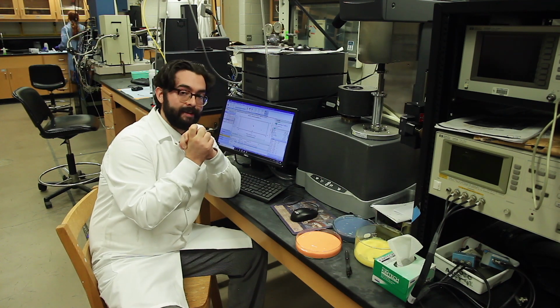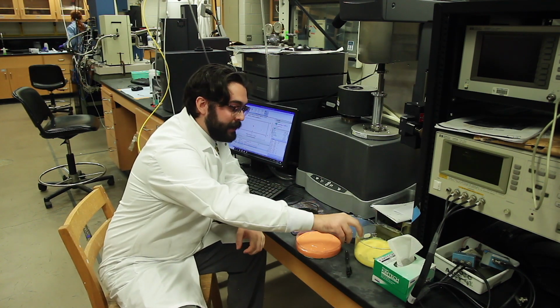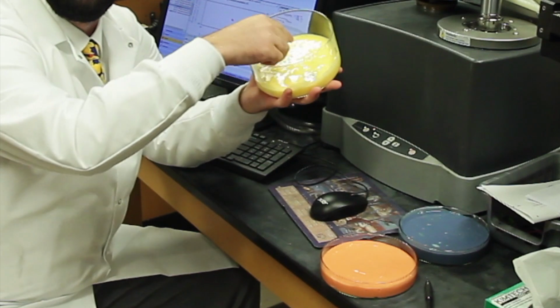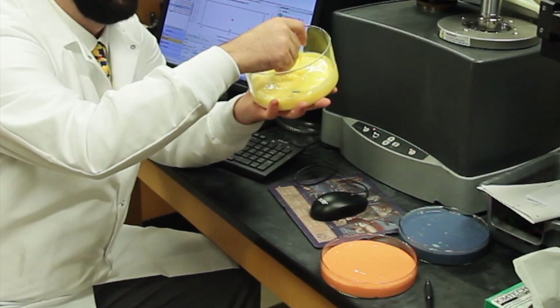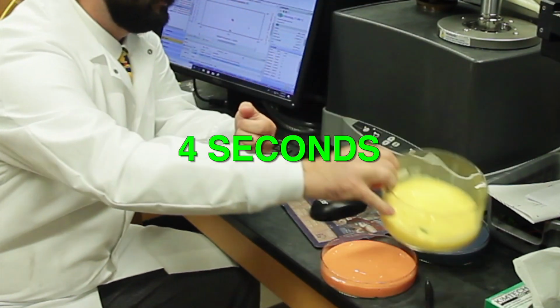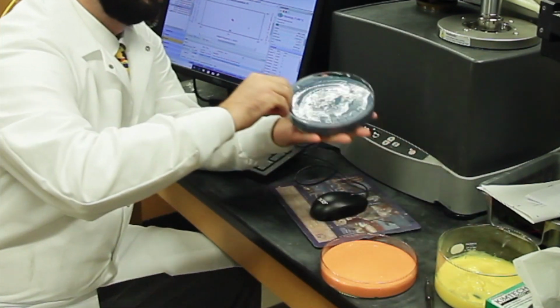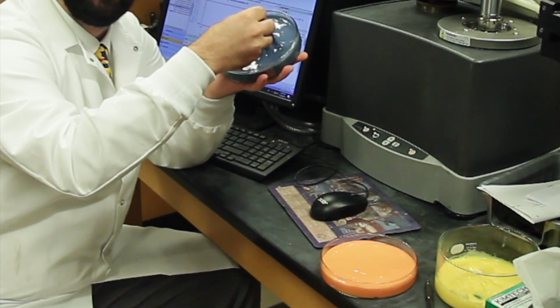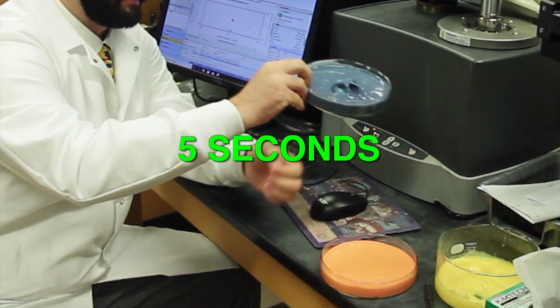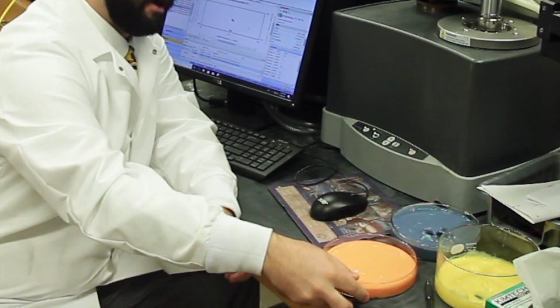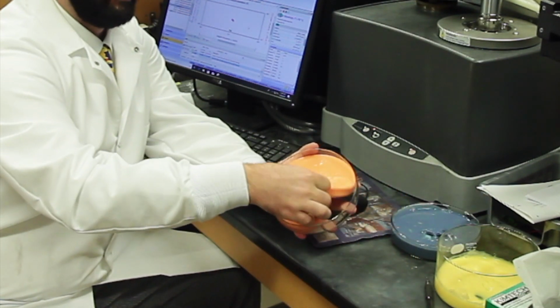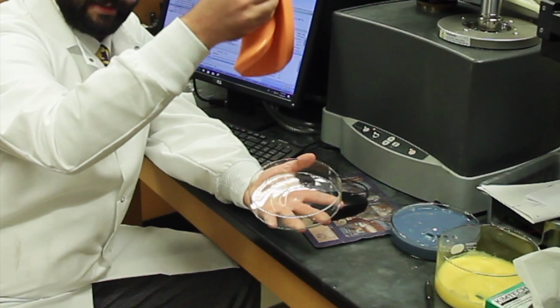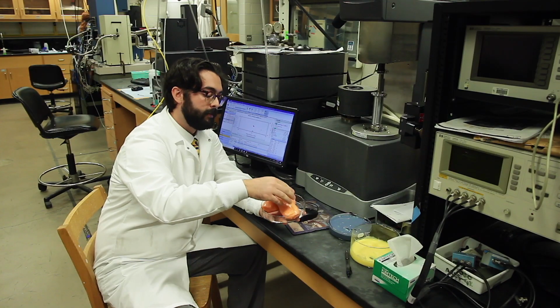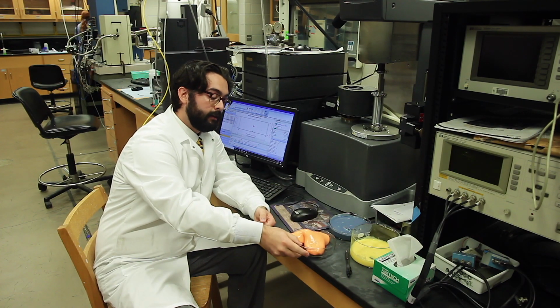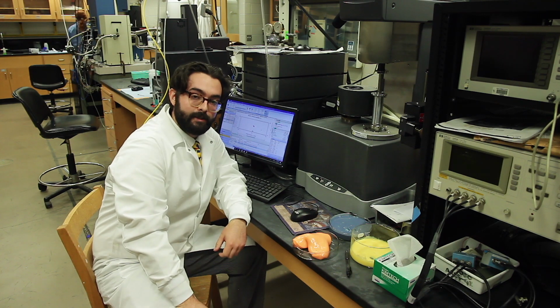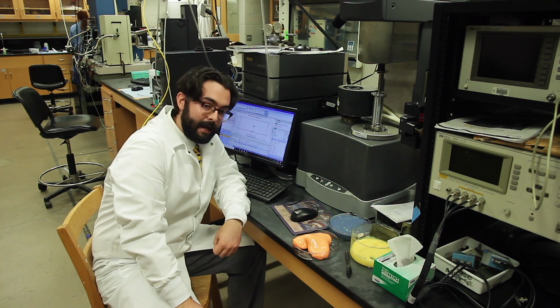So I actually did the calculations, and you may remember our slime that won, the yellow slime, this was 4 seconds. And the slime that lost, the blue slime, that was 5 seconds. And how about one that's entirely different? The harder slime, 10 seconds. So from this, we can see that with a lower relaxation time, we have a slimier material.